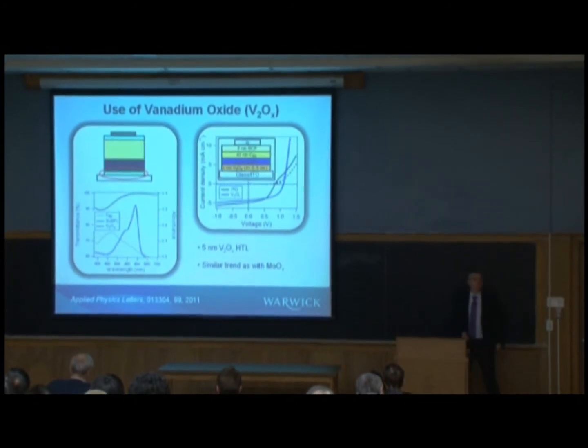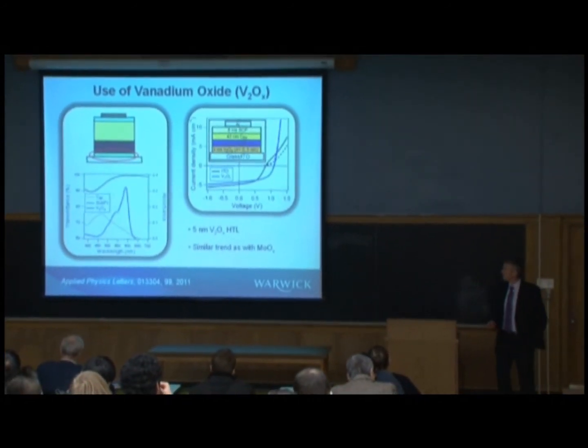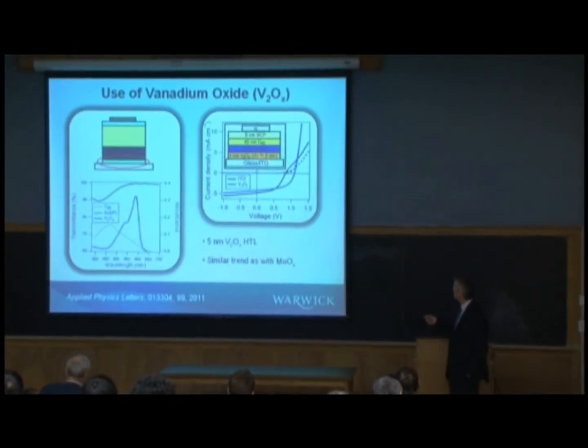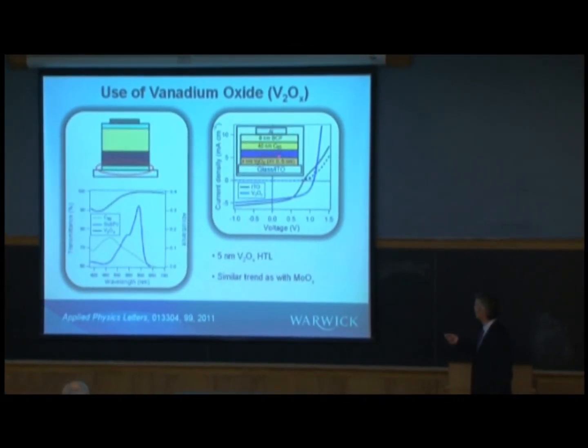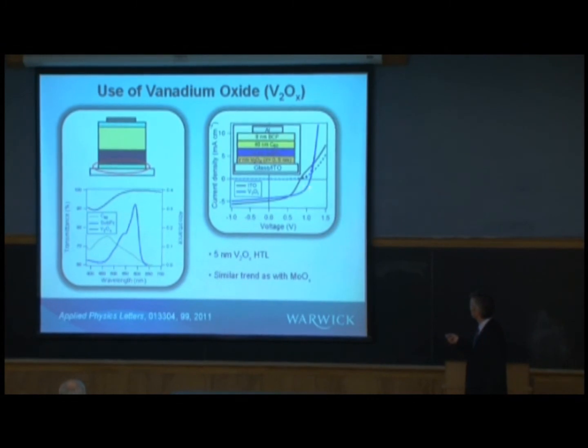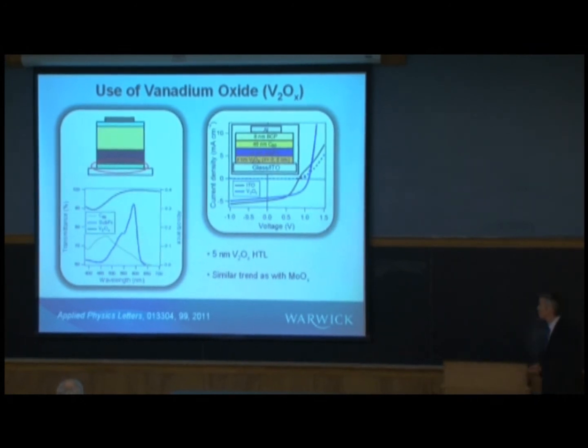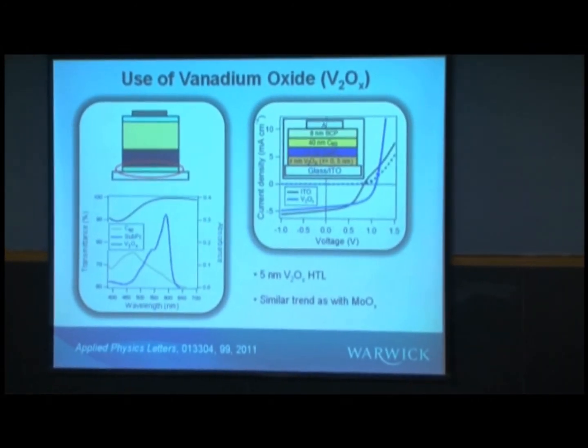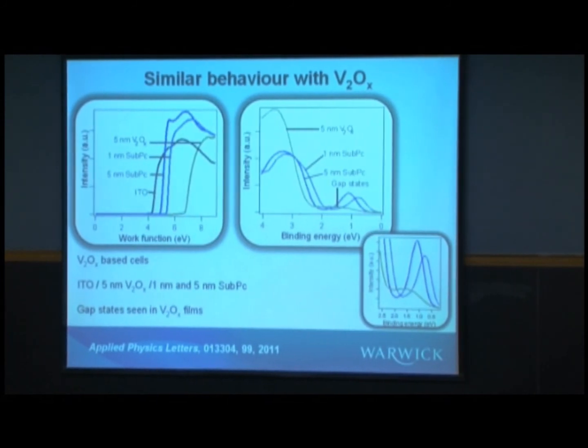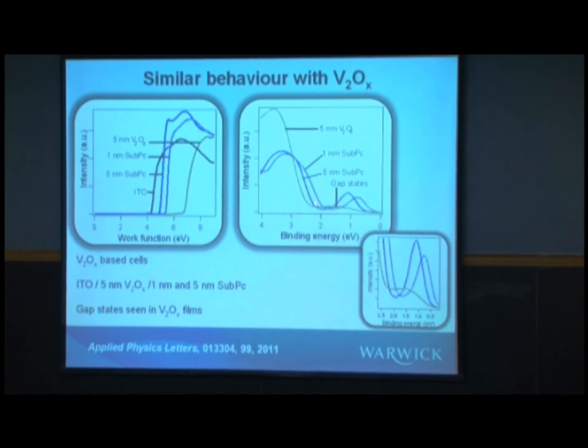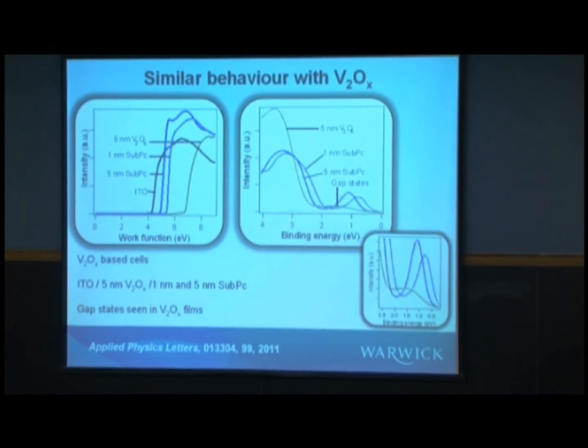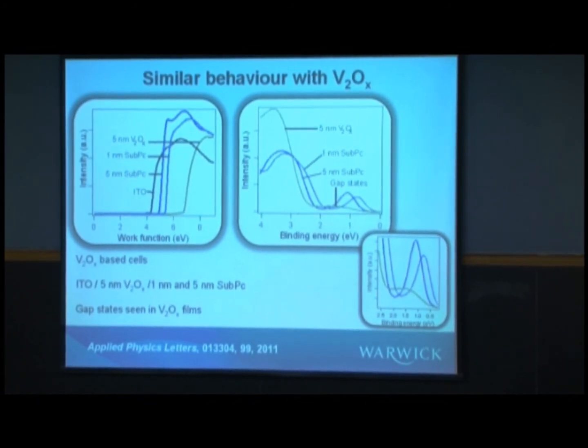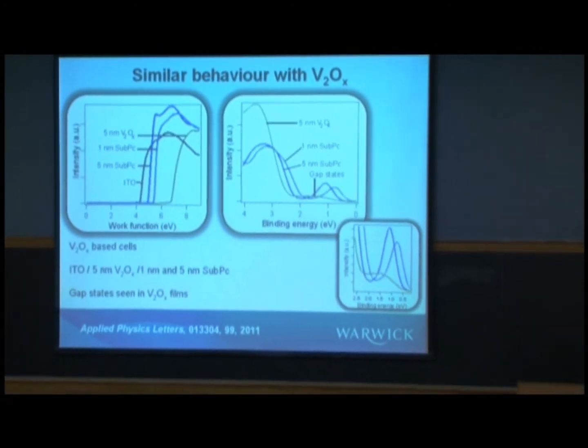Just to show that the same results occur with vanadium oxide, we did the same thing here, putting vanadium oxide in a SubPc/C60 device. Again, these are the current voltage characteristics with a very thin layer of vanadium oxide, much improved compared to without. And again, when you look at the photoemission, it's the existence of these gap states that appear. This is a 5 nanometer layer just below the Fermi energy, which allow efficient charge extraction.